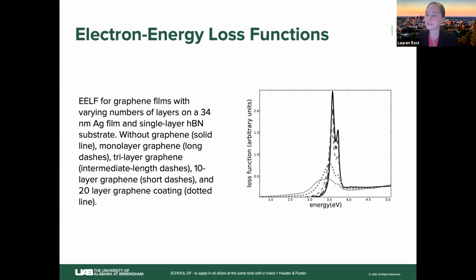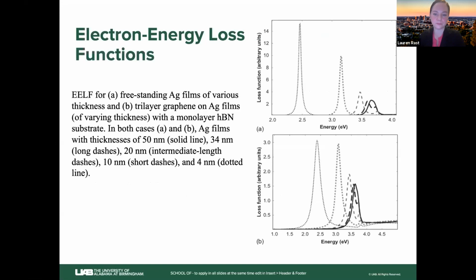Because hexagonal boron nitride is very strongly insulating, the substrate material reduces bulk losses, and it strengthens confinement to the surface modes due to reduced scattering within the material, so confining our plasmons further. And again, we notice that once we start to have a lot of these layers of graphene, we start to get something that looks more like a graphite coating on top, with broadening of that peak.